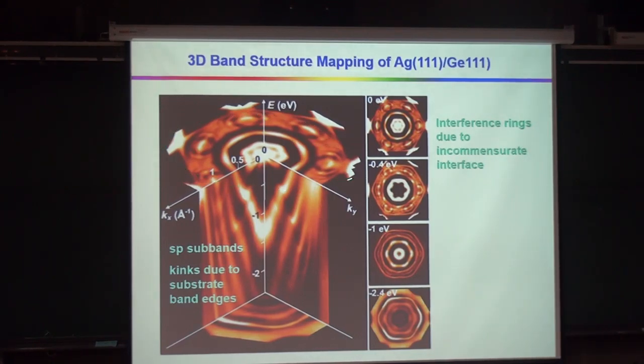And you look at the Fermi surface, the top surface. You see not only these parabolas coming through, the circles, you also got these guys, those coming from diffraction effects. The fact is that we are not dealing with the ideal vacuum slab. Instead, we have atomic structure in the film. The substrate has an atomic structure, and it's got a diffraction grating. So the interface, the electron bouncing back and forth, can give rise to diffraction, and that diffraction gives rise to these additional rings.